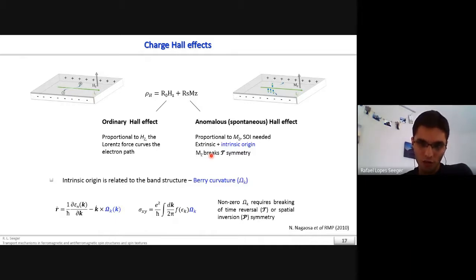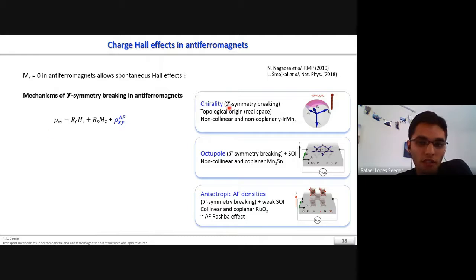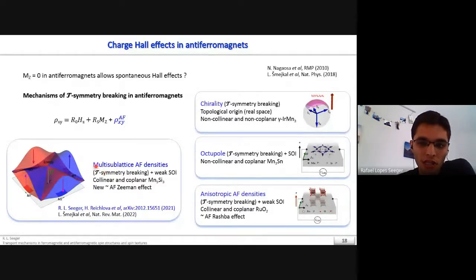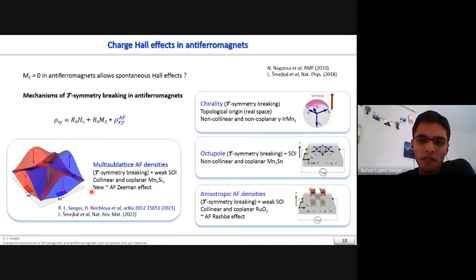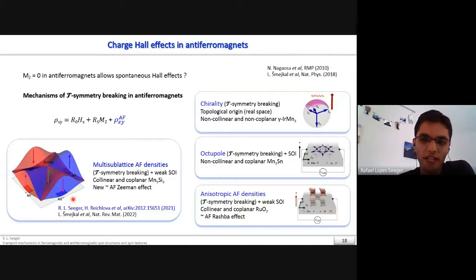To have non-zero Berry curvature, one needs to break specific symmetries. In the anomalous Hall effect in a ferromagnet, it is the out-of-plane component of the magnetization that breaks time reversal symmetry. From this symmetry perspective, it was believed that in antiferromagnets no Hall contribution would be observed due to zero net magnetization. However, recent developments have shown that you can break time reversal symmetry in non-collinear and non-coplanar antiferromagnets even with zero net magnetization, and it can also happen in collinear antiferromagnets due to anisotropy in magnetization densities. In our work, we introduced a new time reversal symmetry breaking mechanism in collinear antiferromagnets coming from the interplay between antiferromagnetism and crystal symmetries, which we demonstrated by measuring a spontaneous Hall effect in Mn5Si3.